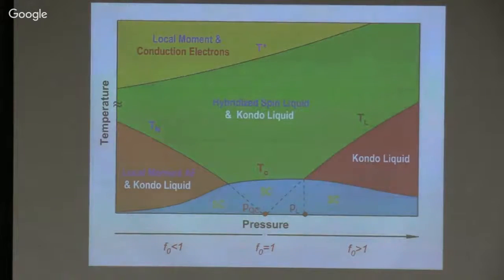So this is what the phase diagram looks like. At high temperatures, you've got local moments interacting with the nearest neighbor interaction and conduction electrons. And you see Curie-Weiss behavior in the uniform spin susceptibility. Go down below T star, the system begins to hybridize. So the Kondo liquid emerges, and you've still got the spins around, but they're hybridized now, so they have a different strength than they did before. So they form, if you like, a spin liquid of interacting local moments.